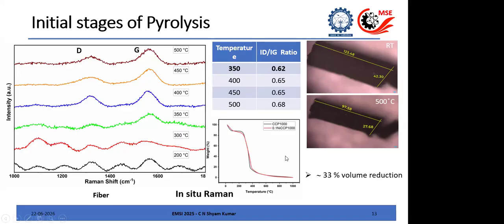So this is something called a TGA. It measures the weight loss of your sample while heating. So you can understand at what temperature the volatiles are starting to separate out from the sample, and you can correlate it with the Raman. Why we did this was that we can now understand at what temperature the initial carbonaceous backbone is forming.